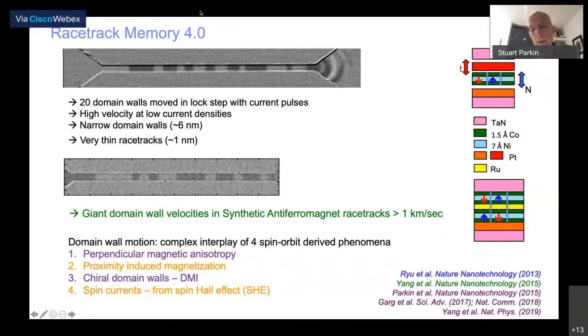It's caused by spin-orbit torques, which are derived from an interplay of 4 spin-orbit coupling-derived phenomena: perpendicular magnetic anisotropy, proximity-induced magnetization, chiral domain walls due to a Dzyaloshinskii-Moriya exchange interaction, and spin currents derived from spin-Hall effects. And these spin-Hall effects in platinum and tungsten are much larger than people had ever anticipated. They're of the order of 20, 30%, even 40% in some new materials we've recently discovered, making, again, racetrack very, very interesting. This is what I wanted to say about racetrack.